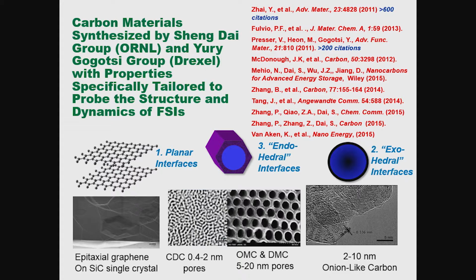So this is just 3 examples of graphenic materials with planar structure. Majid talked about carbide-derived carbons with very high porosity and very small pore sizes, very tight ranges of pore size distribution. Sol-gel synthesized ordered and disordered mesoporous carbons with larger pore sizes but very uniform pore sizes, and these materials that don't exhibit internal porosity but external high surface area, so exohedral interfaces, these carbon onions and materials like that.